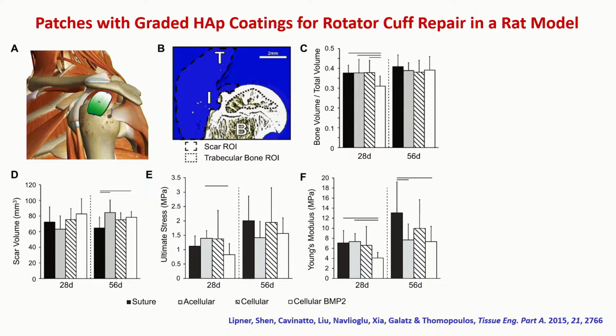And the last group is also a cell-based scaffold, but in this case, the cells have been further transduced with BMP2. It's bone morphogenetic protein. It's kind of like a growth factor that can enhance osteoblast differentiation. Unfortunately, when we compare the performance of these 4 groups by different measures, we didn't see much enhancement, okay, when we apply these patches with the cells.